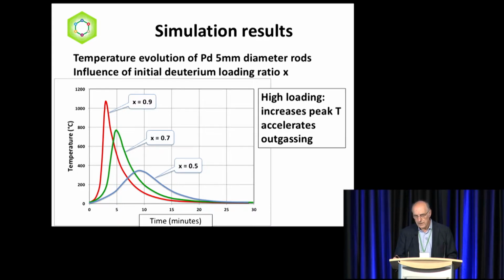If you have different initial loading ratios, it's interesting because the highest loading ratio gives a higher temperature and it lasts a shorter time. And if you have a small loading ratio, the maximum temperature is lower, but it lasts longer.